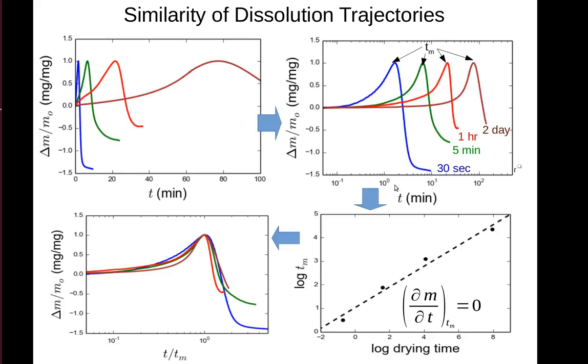For instance, if we were to inspect what would happen at 2 hours, we would take our master curve, look at 2 hours, and find what the scaling is, and then we would apply the inverse of that scaling to get back what the dissolution time would be at 2 hours of drying.